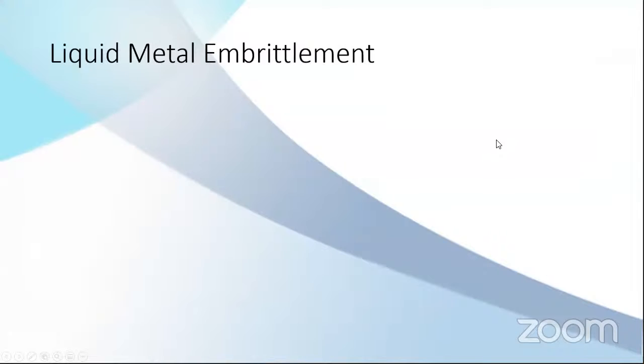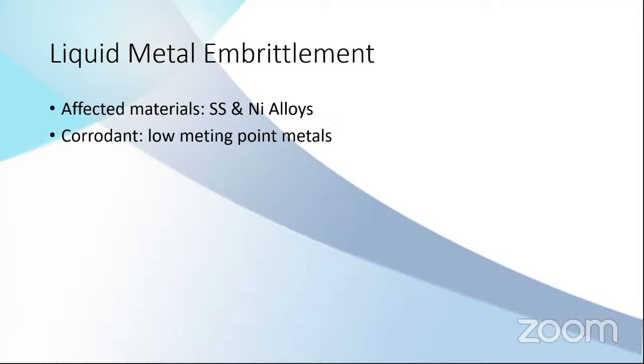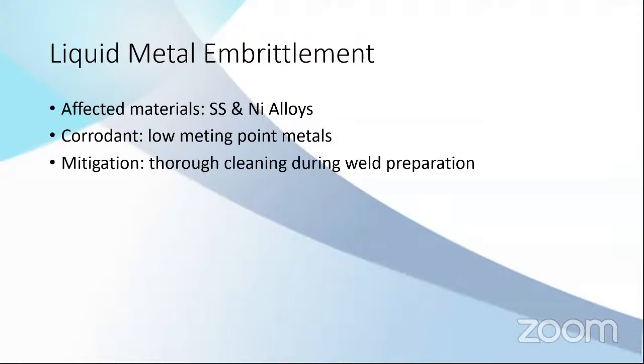Liquid metal embrittlement, I consider this as corrosion, but actually you can consider this as impurities, not corrosion. The affected materials are stainless steel and nickel based alloys as well. So the corrodants are low melting point metals. This is not from the fluid, not from the surface, but normally it's from contamination. So the mitigation is to clean the materials thoroughly, especially the joint. So you have a very clean joint preparation.